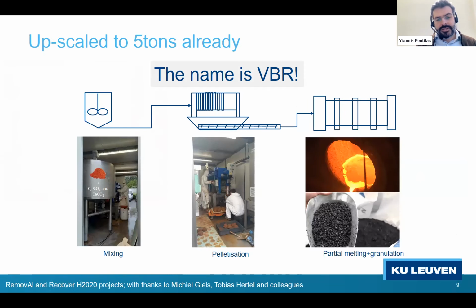How would you do that on a bigger scale? We have our own containers, but it's not that difficult after all. You just add your precursor, your residue in this case, with the silica, the alumina, and the calcium. You can add 2% or 4% of carbon. Then it's a filter press at the back. You produce what we call in the lab our sausages, with the components inside.